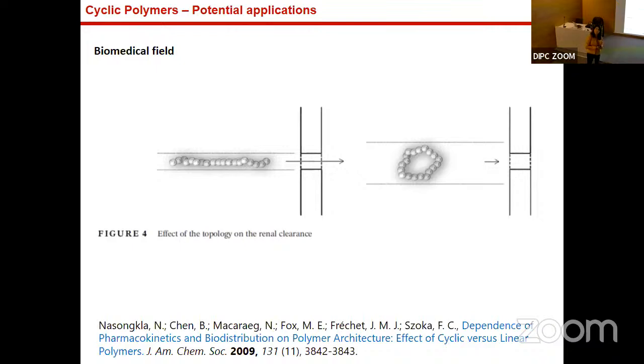At the beginning of your talk, you showed different diagrams with the theta or glass temperature, these heat capacity thermograms, and then these measurements of solubility, which I guess point at the single molecule or dilute behavior and the phase behavior of the polymers. I don't know if you're aware of the relationship that has been found between the theta temperature and the critical temperature for intrinsically disordered proteins. That is very nice because it connects the single molecule properties with the phase behavior. I was wondering if anything like this has been done for circular and linear polymers to relate both things.